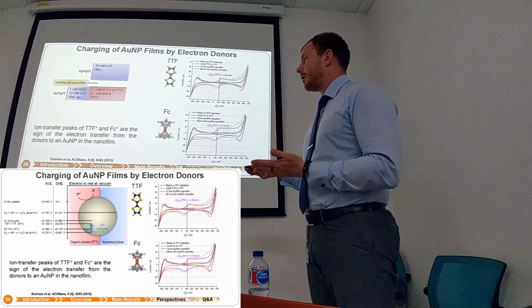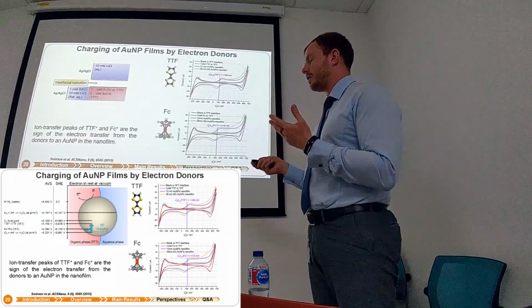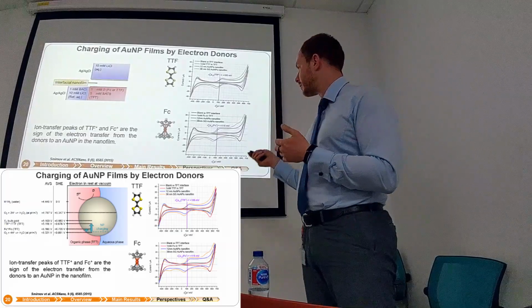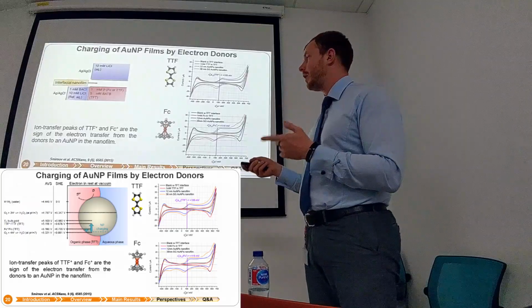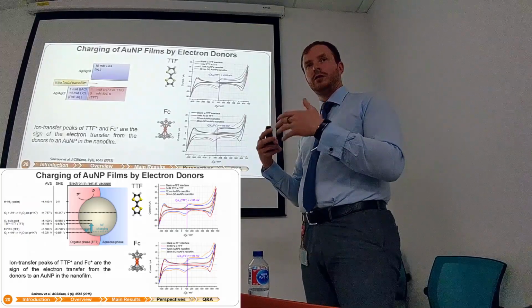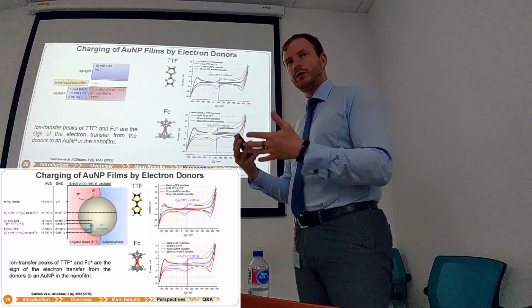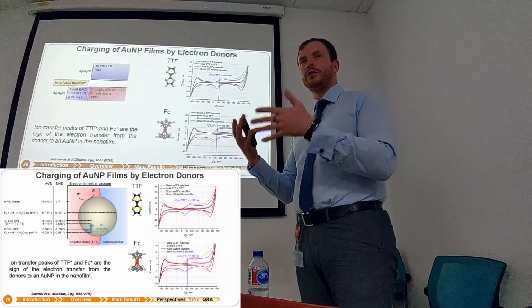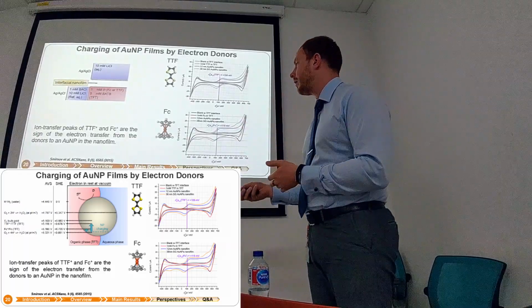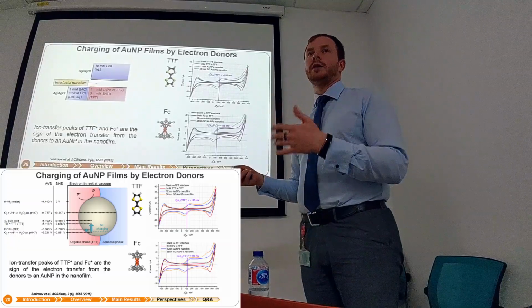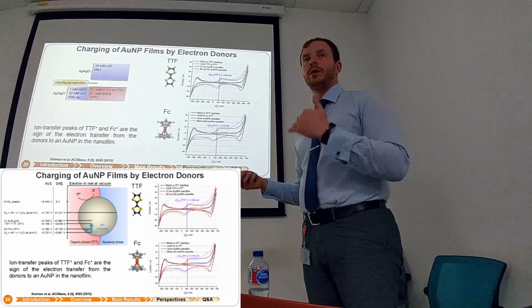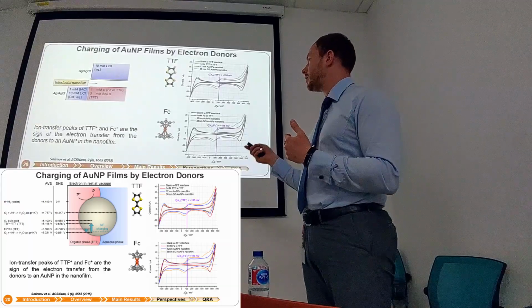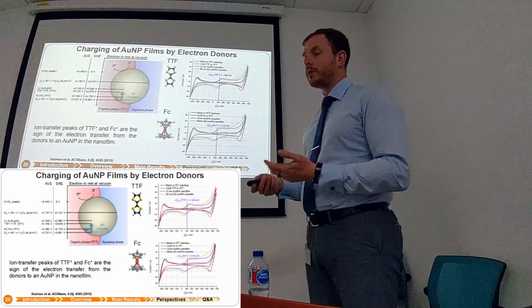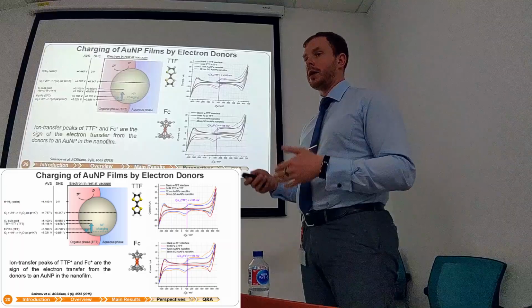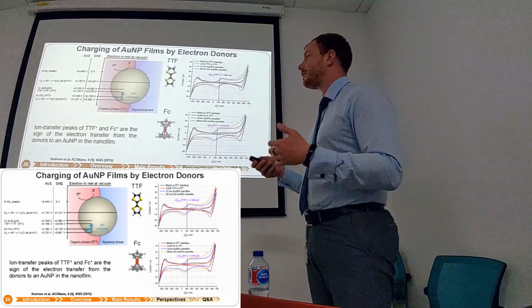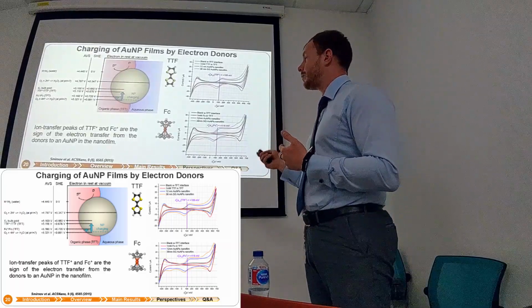So these ion transfer peaks of TTF plus and ferrocene plus, because these are peaks of ion transfer, are a sign that those donors gave the electron to nanoparticles. And this means that nanoparticles are kind of positively charged, or their potential is lower than all this stuff. And based on that, we developed a theory explaining all these observed phenomena.